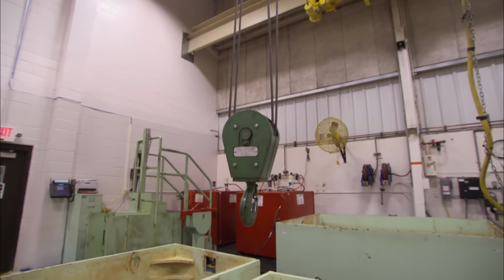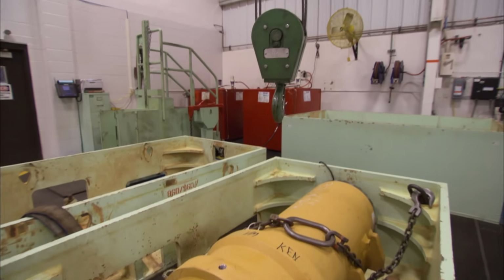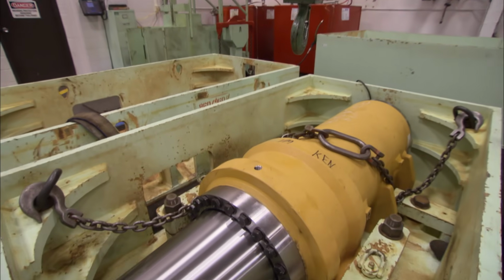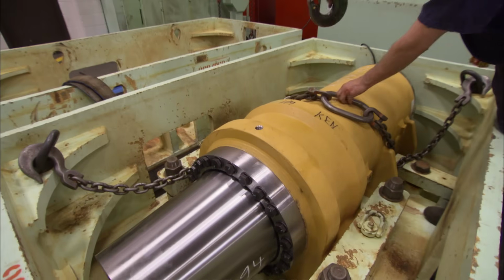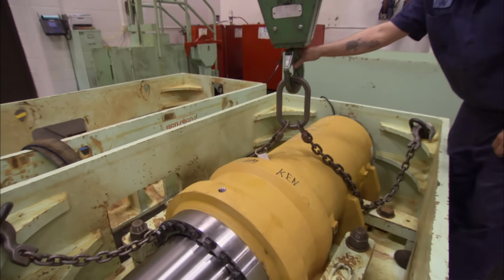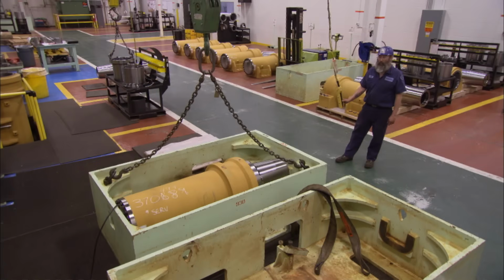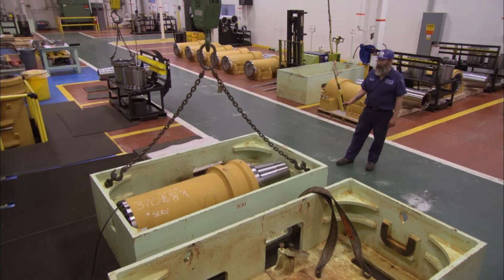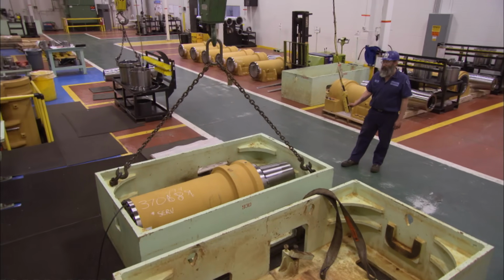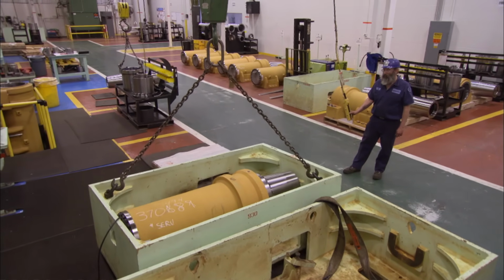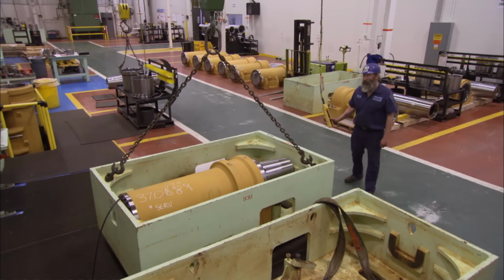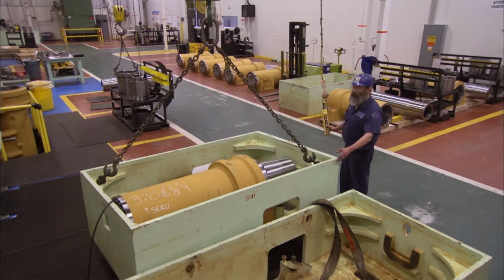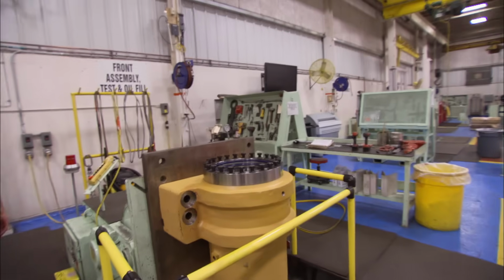The final step is testing. Technicians must make absolutely sure the chrome plating dimensions are perfect and no air can escape, even under 500 tons of weight. To test the system, the chrome-plated piston and suspension housing are bolted into a steel box, nicknamed the casket. This box is an important precautionary measure.